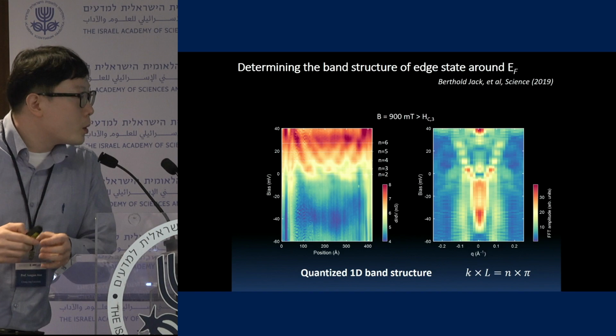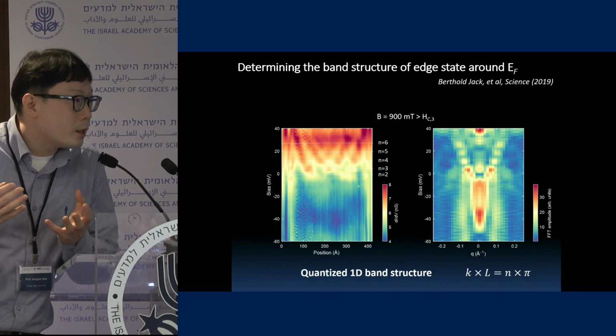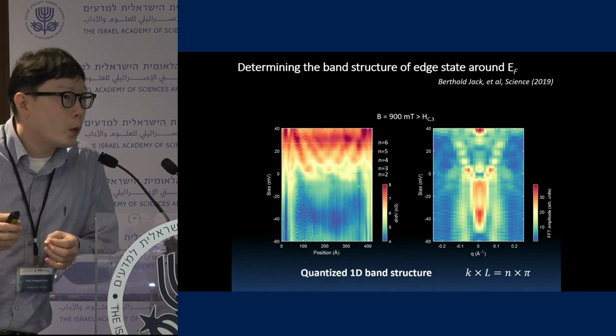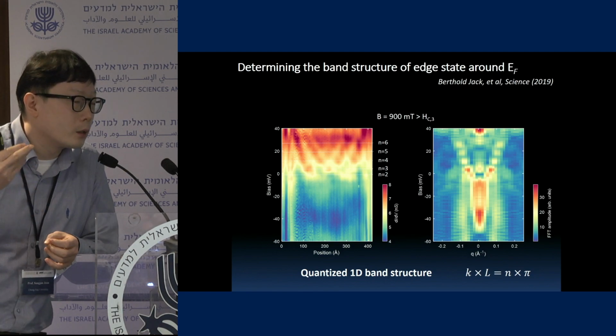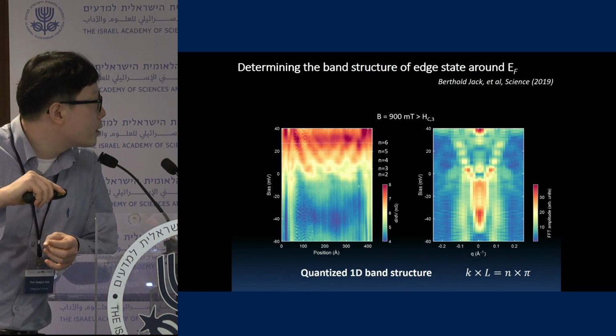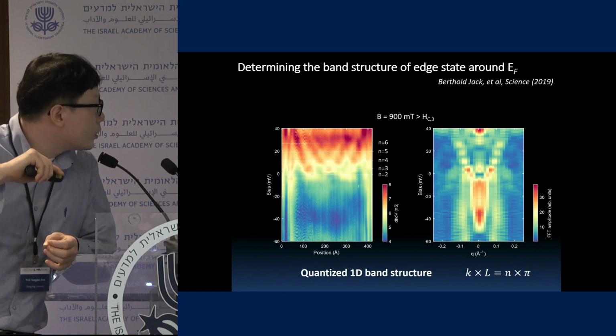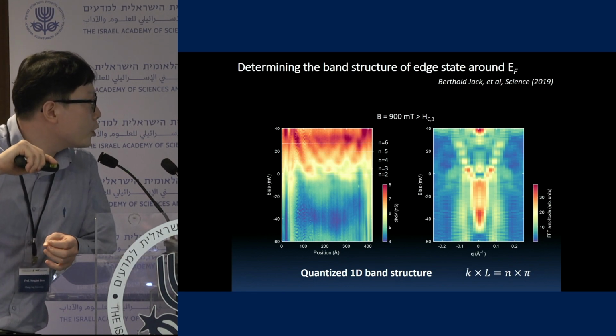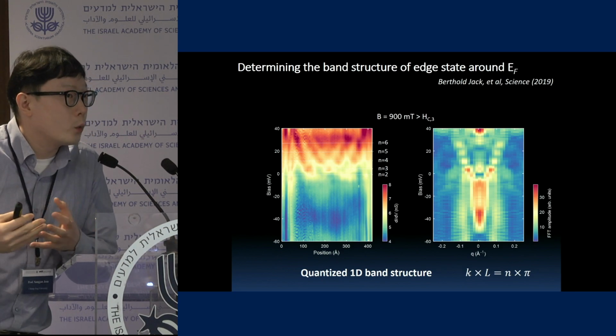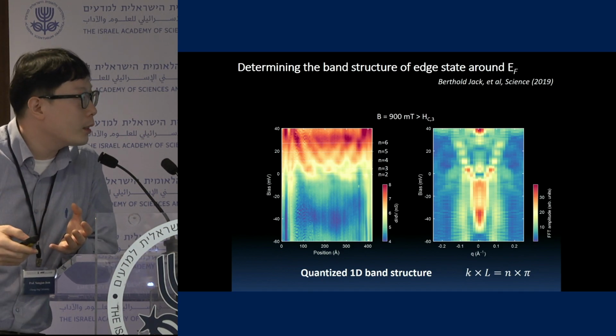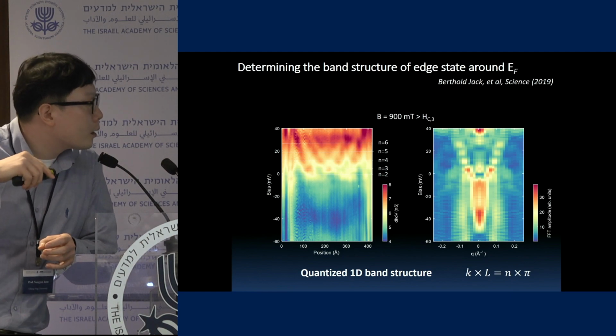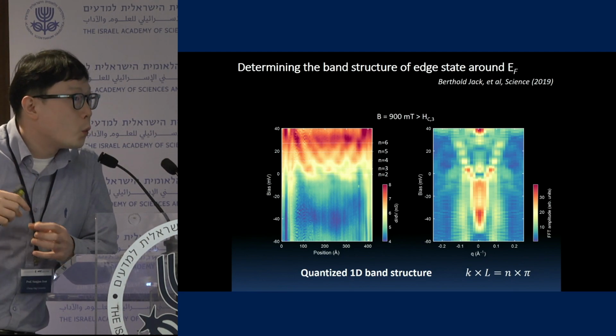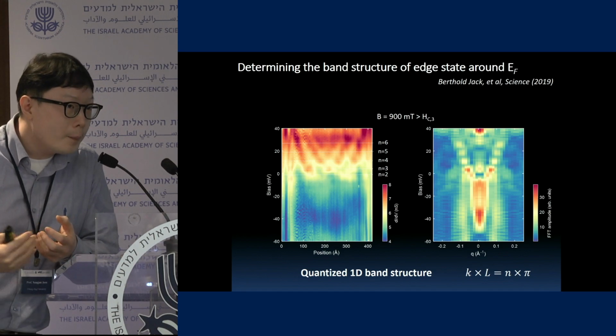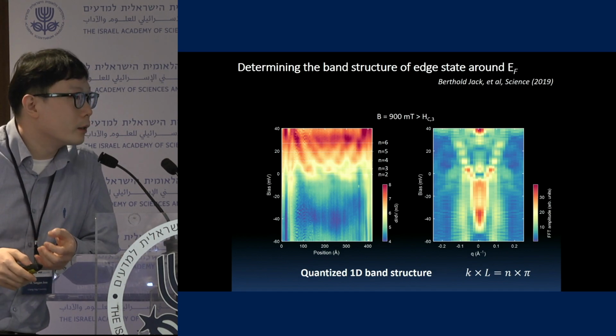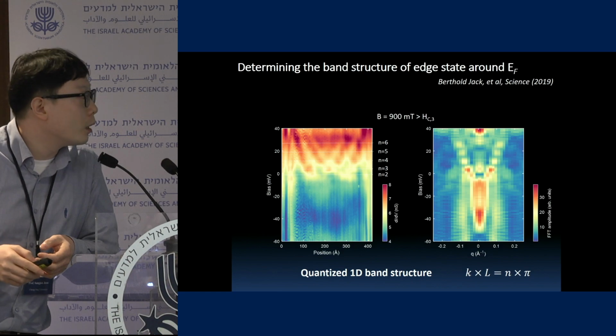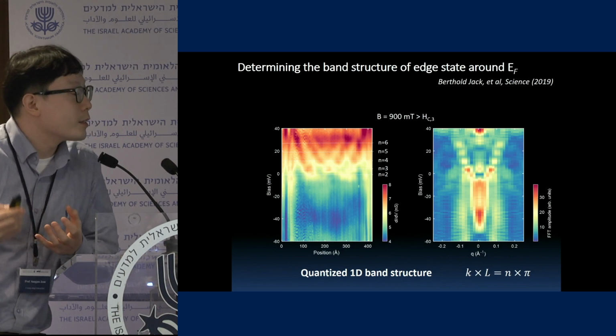Of course, we have to check how many states are there at the Fermi level where we wanted to get some topologically non-trivial states. So basically, we measure the density of states as a function of position along the edges, which we did before on a bulk state, and this is the thin film state. Then we found that only one state passes through the Fermi energy, which is related to an odd crossing number of the surface states, edge states.